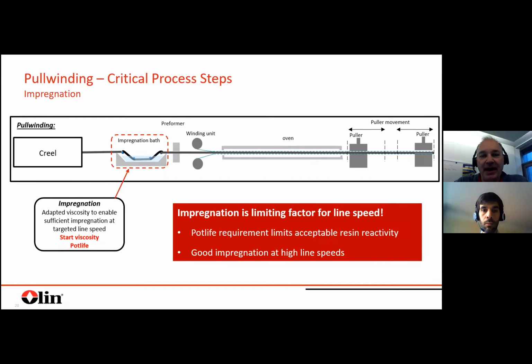But it's not only the resin which defines what kind of line speed can be achieved. It's really the combination with the impregnation. So and this is something which can be optimized. We have a lot of ideas around. I will come to this later. But this is something which should be in mind, that if we discuss productivity, it's as usual the combination of material and process which have to be optimized. And the key is here for this process really the impregnation unit.